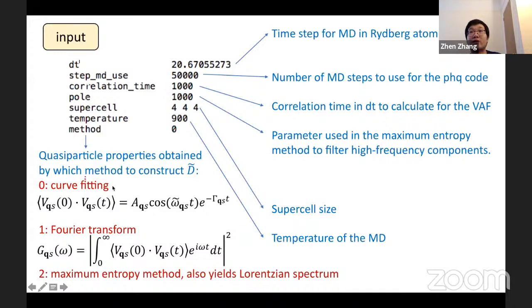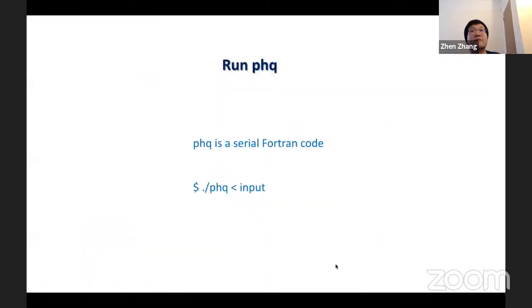For example, when method equals 0, it means the curve fitting method is used. The VAF is fit to an exponentially decaying cosine function. Method equals 1 means the Fourier transform is used, and the Lorentzian shaped power spectrum is used to obtain phonon quasi-particle properties. And the maximum entropy is another method to obtain the quasi-particle properties, which should also yield the Lorentzian spectrum. So PHQ is a serial Fortran code. After compiling the code, simply type this command to run the program.